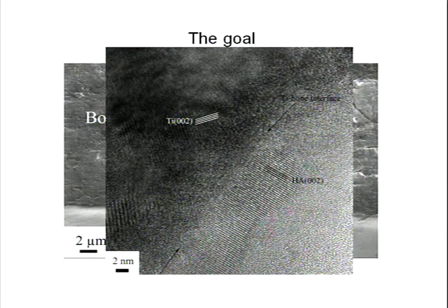And you see the atoms, the atomic lattice, the ordered appearance of hydroxyapatite on the right. But on the left, you see an equally ordered titanium atomic lattice. So we have a meeting between living and dead where the atomic planes interact.